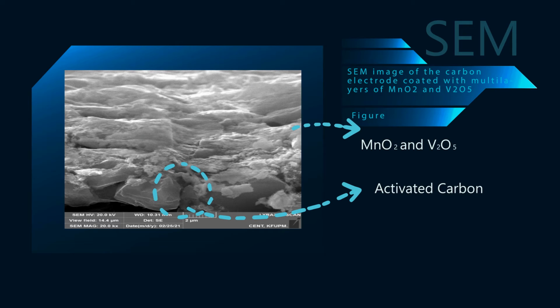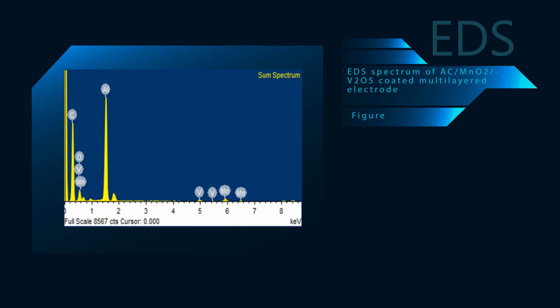In this image, we can clearly see the activated carbon electrode coated with a thin layer of manganese oxide and vanadium oxide. The image shows micro-sized particles of activated carbon coated with the metal oxide. The elemental composition of each element used in the fabrication of the multi-layered electrode is analyzed using the EDS spectrum. Clearly, the figure shows all elements used to fabricate a supercapattery.